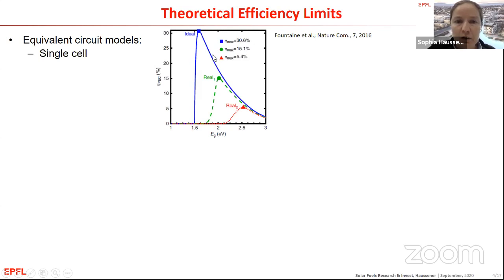For an ideal situation here in blue, which would basically neglect any kind of overpotential you could have in your chemical reactions or any kind of transport limitations you can have in the semiconductor. And then she also introduced 2 more realistic cases. But effectively what you can see is the peak efficiencies are in the range of 30%, so certainly quite an interesting efficiency. So if you have worse catalysis or worse photoabsorber, of course, the peak efficiency comes down.